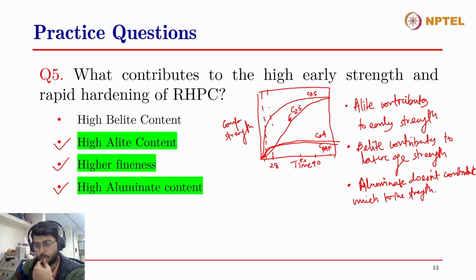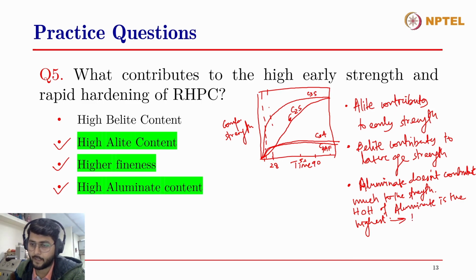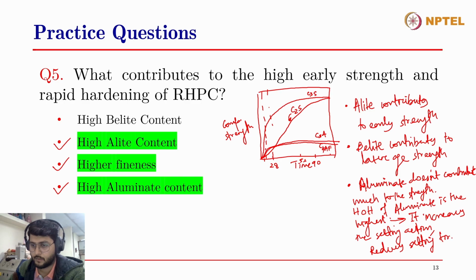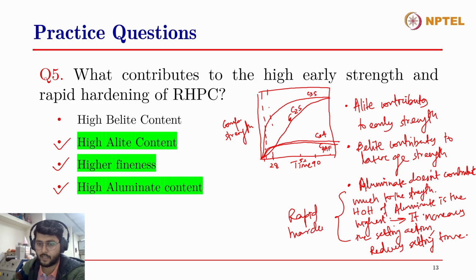However, the heat of hydration of aluminate is the highest, and therefore it increases the setting action, or reduces the setting time. So aluminate contributes to rapid hardening, meaning that it makes the concrete set early, while A-lite contributes to early strength.